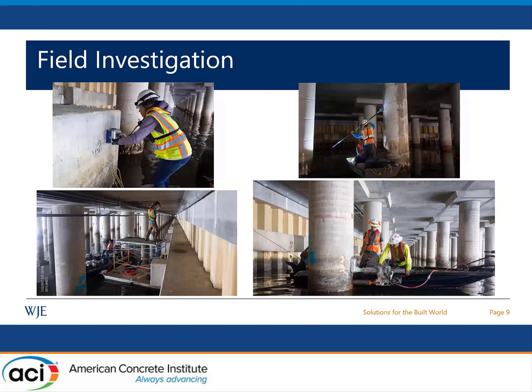So the objective of our investigation was to characterize the current condition of the existing structure to provide a basis for the repair recommendation. And to do that, we followed the same approach I mentioned earlier for field investigation, where we started with element level visual inspection of all accessible elements, and then we selected representative study areas for in-depth assessment, including cover measurement, corrosion NDE, and collecting material samples.